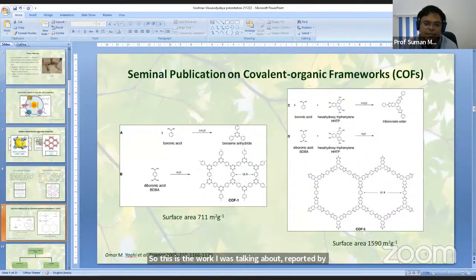Now, going further forward, this is the work I was talking about, reported by Omar Yaghi in Science, where you can see that boronic acids can be utilized together to form a triangular unit by dehydration. They used only organic material mostly because they wanted to make porous material which is lightweight. If you use metals, the weight becomes higher. And when this diboronic acid is treated at high temperature, a polymeric structure with pores comes about, and you can see the pore diameter is something like 1.5 nanometer or 15 angstrom.